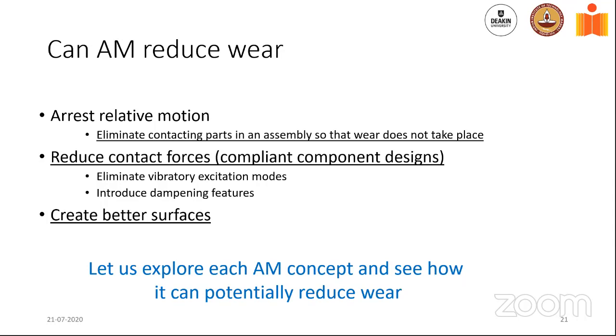Second one essentially is, as I said to you before, when the contact stress is high, the wear is high. When the contact stress is low, the wear is low. There may be exceptions here and there, but this is a rule. This is largely true. If I had a component loaded to, let's say, 1 KSI, and I had another set of components loaded at 10 KSI, and the materials are the same, you're going to find out that at 10 KSI, the wear is much higher. May not be 10 times higher, but definitely much higher.